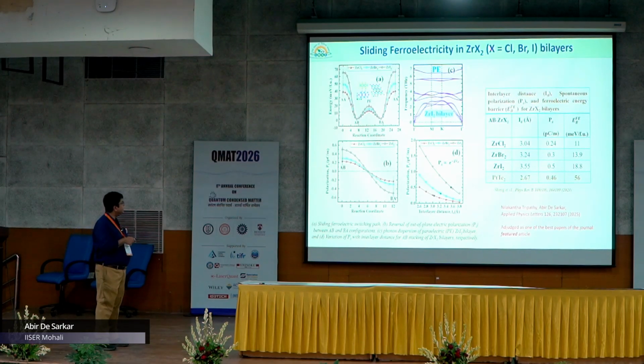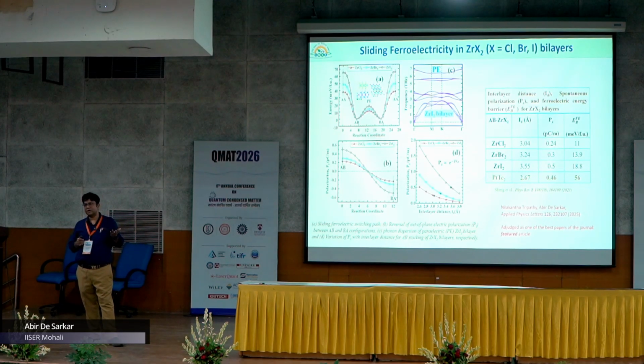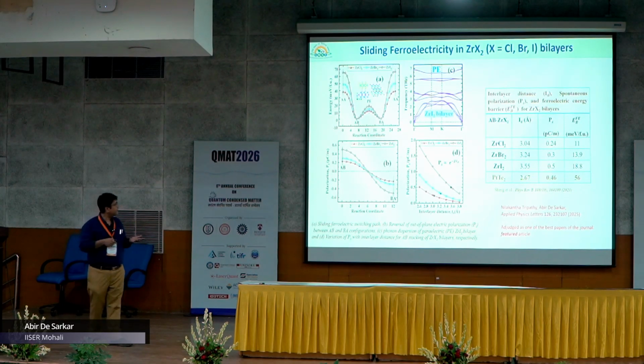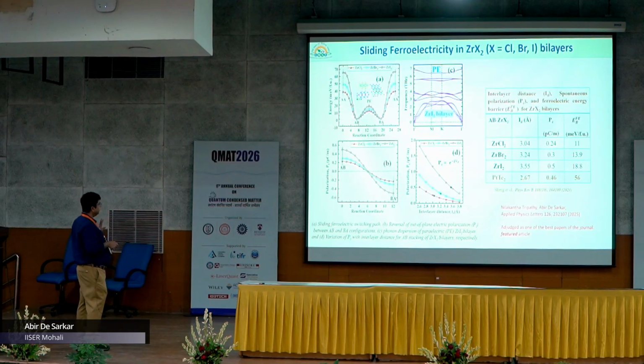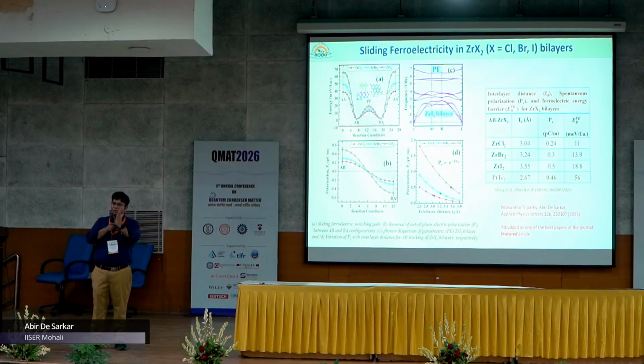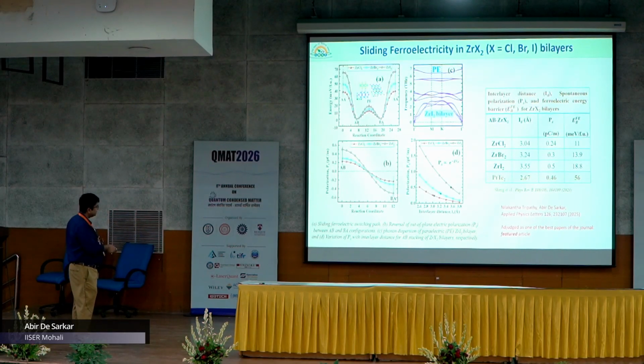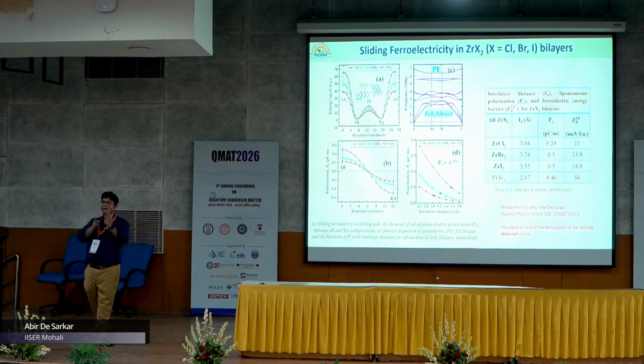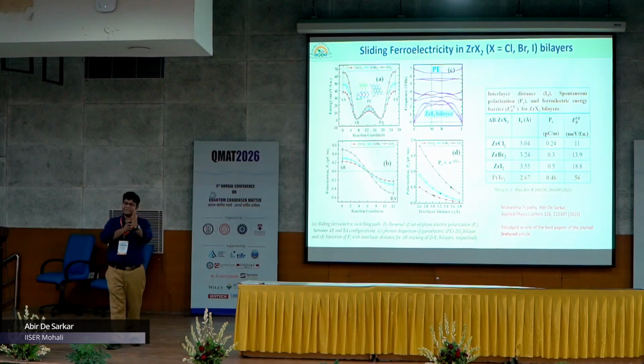And now they are isostructural with MoS2. They have nearly the same structure as that of MoS2, and in the AB stacking sequence, the polarization direction is along the plus Z direction, and as you slide one layer on top of the other, the polarization direction reverses itself from plus P to minus P. So this is the sliding ferroelectricity, and as you are sliding one layer on top of the other, you are going from AB stacking sequence to BA stacking sequence.